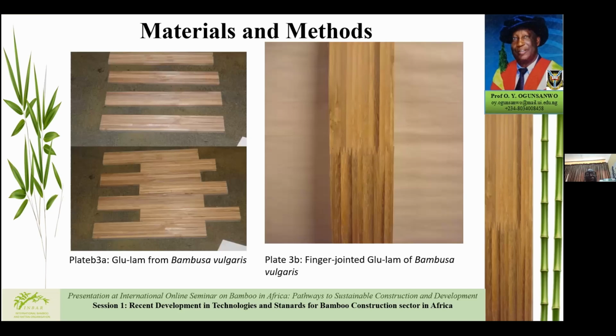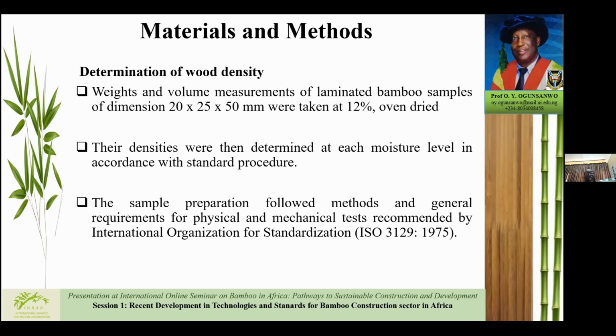And from what we observed, these samples in plate 3A and 3B were the results. Samples of bamboo glulam are in plate A, while plate B gives us a finger-jointed glulam of Bambusa vulgaris. You can see the line of the finger joints on plate B. Wood density was determined using a dimension of 20 by 25 by 50, and samples were taken at 12% moisture content. In the sample preparation, we made sure that it followed methods and general requirements for physical and mechanical tests recommended by international standards.